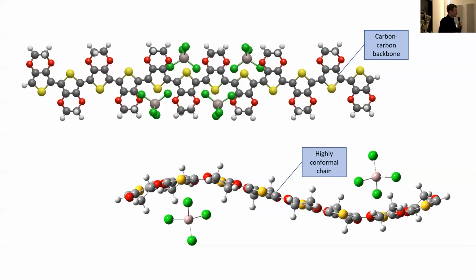One of the things they theorized from their experimental results and from early computational methods, such as one-electron theories and semi-empirical methods, which were all that were affordable computationally at the time, was that as you bring in one anion, it creates a structural distortion along the polymer backbone. But as you introduce another one, there would be an energy driver for the 2 anions to co-locate despite the coulombic repulsion between them.